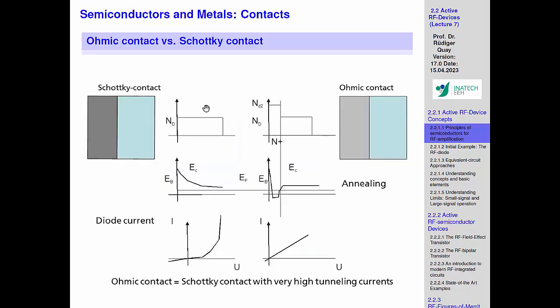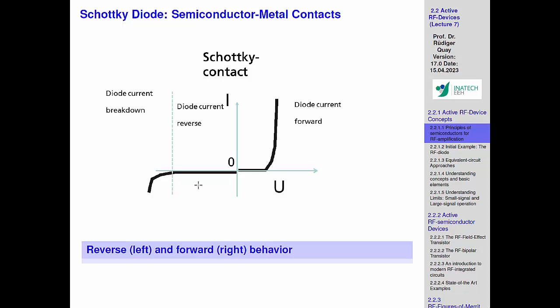There are two characteristics of the Schottky contact. So this is for zero bias, and if you put a potential to this Schottky contact, then you can attract electrons again, so that at some point they go near the interface and in, and then you get an exponential behavior. And if you increase this distance by putting a negative voltage, then you make this depletion region even bigger. Yeah? So that's helpful. And then what you get as a current characteristic is a reverse current, where you can use the contact nicely. And then at some point when it's too high, it simply breaks down also. Yeah?